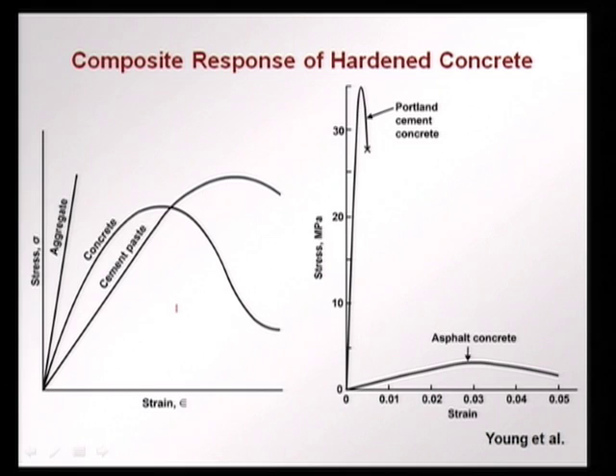What is interesting is that concrete has initially a linear elastic response, followed by a non-linear response, the peak load and softening. Remember, when we talked about the response of materials to stress, we saw that materials such as concrete, rock and so on have this softening type response. Initially there is no cracking within the concrete, then micro cracks start to form, maybe in the interfaces between the aggregate and the mortar or the cement paste. These cracks start linking up, they reach a certain point when the concrete cannot take any further load, the cracks develop, leading to a decrease in the load carrying capacity, and therefore you have this softening.